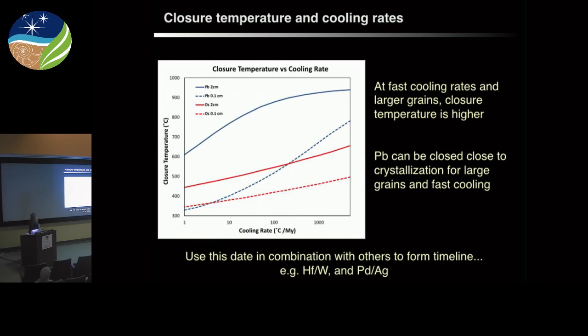Okay, so that's just what this says here. With fast cooling rates and larger grains, the closure temperature is much higher for lead. It can be closely pinned even to solidification of the iron sulfide. And we can use these dates in combination with others, including palladium-silver and hafnium-tungsten, to start to get a picture of the sequencing of things.